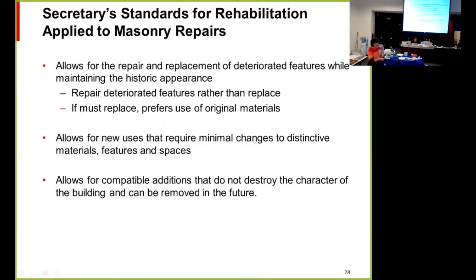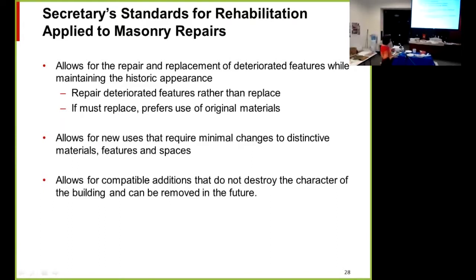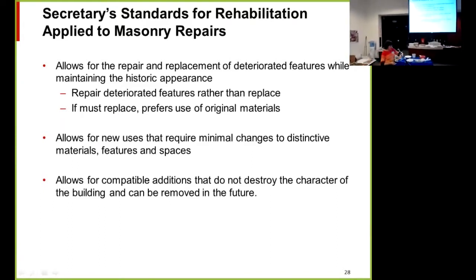How the Secretary of the Interior's Standards applies. It allows for the repair and replacement of deteriorated features while maintaining the historic appearance. So generally, we try to repair rather than replace. Sometimes we have to replace features either because they're too deteriorated to repair or they're covering something that is the root cause of the problem. So for example, that column cracking that I showed you, because the steel underneath it is corroding. There's not really any way to repair the steel except to take the terracotta off, clean up and paint the steel, and replace it.